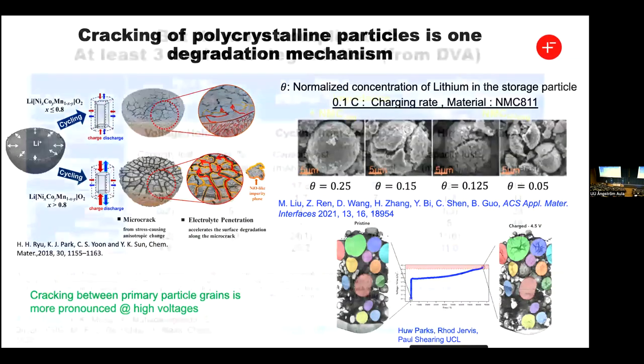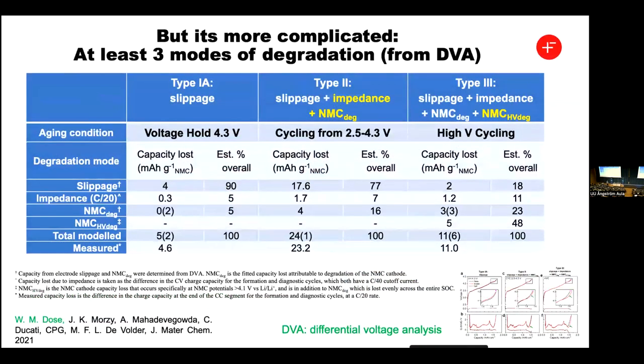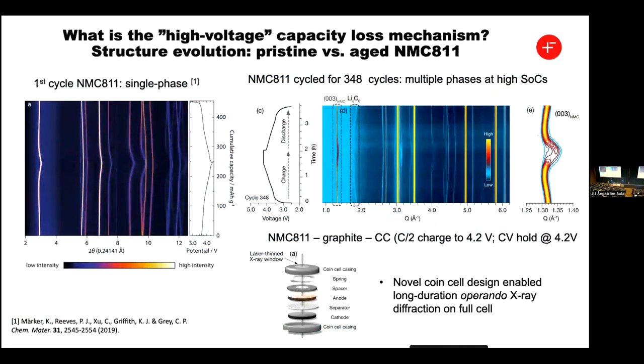So what Wes did then was to pull the whole thing out with his DVA, differential voltage analysis, and work out the different types of modes depending on the nature of the cycling. If you just have a voltage hold, all you get is slippage at the anode. So all this junk that comes off at the cathode causes more degradation on the anode. If you start cycling, you get the slippage, you get an impedance growth on the NMC, and you also get a degradation mechanism of the NMC itself. And then if you have the final one, where you just have high voltage capacity cycling, you get an additional degradation process on the cathode itself. So let's unpick some more of these different processes.